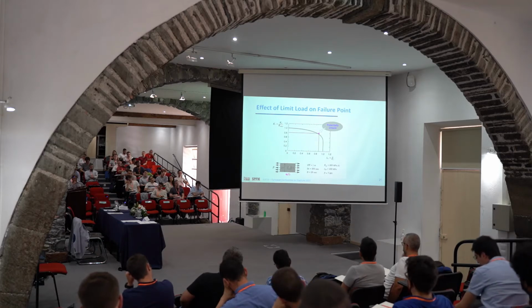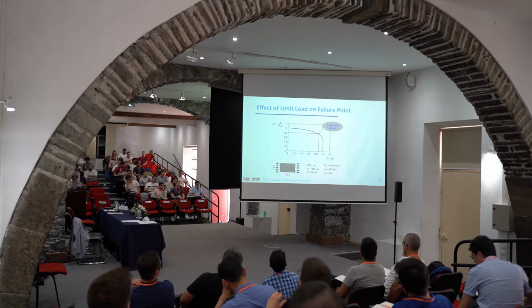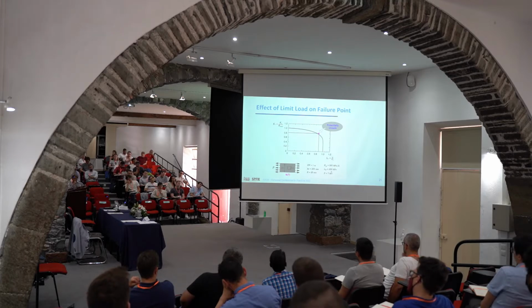If you consider only the yielding of the ligament, this is the ligament here. If you consider only the yielding and do the math here, you find out that your applied stress in the remaining ligament here is less than the yield stress. Again, forget about the safety factor, but that means that your ligament has not yielded, so your structure is safe.